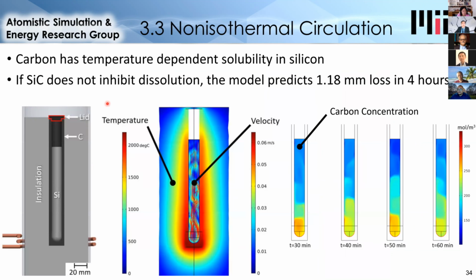Now, the next challenge to investigate was the effect of non-isothermal circulation. Because we've shown that carbon has a temperature-dependent solubility in silicon, if the silicon carbide layer doesn't prevent the carbon dissolving, then I modeled the effect of this dissolution in COMSOL and estimated that we would lose about 1.2 millimeters of the wall in the hot zone of graphite over the course of 4 hours. So if this happens, this means that the graphite is dissolving very rapidly, which would prevent the system from lasting the years needed for commercial application.